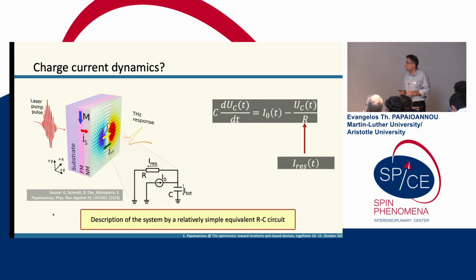We can explain this effect in terms of a simple RC circuit. So in principle, what do you have? You have your laser, you induce your spin current, then you have the charge current. The charge current charges this metal film, and then you have a kind of discharging. So it's like with your initial current, you charge a condensator, and then you discharge the condensator with this backflow current.